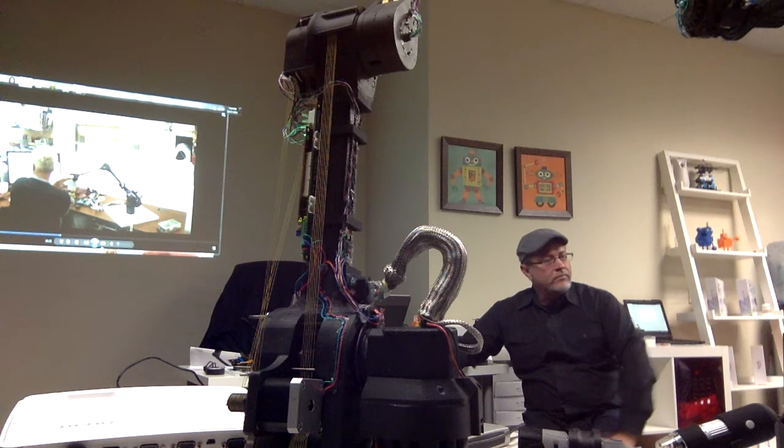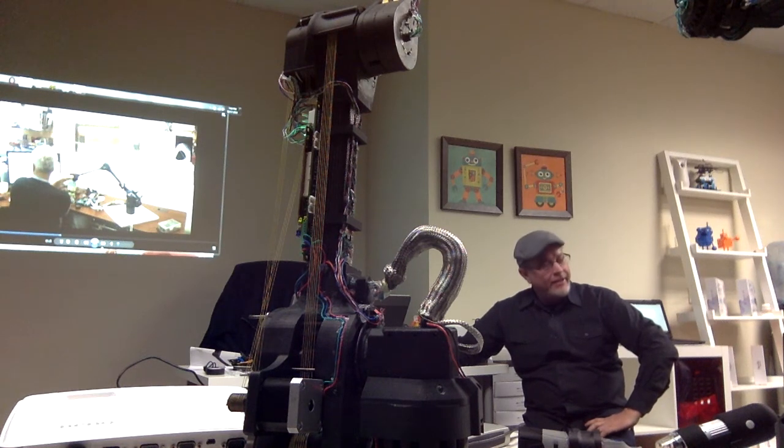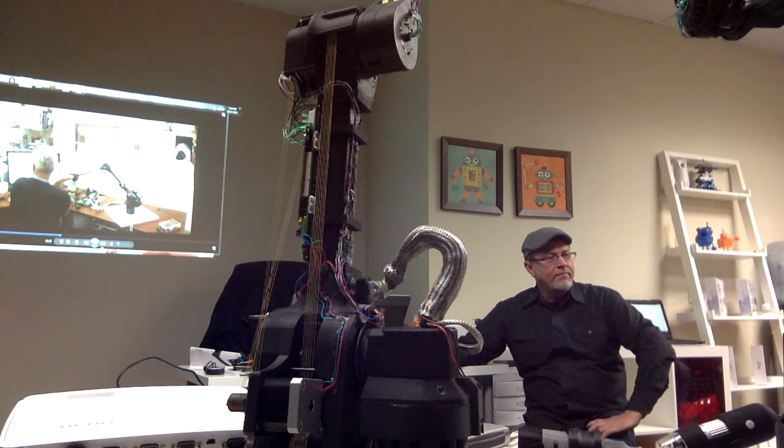So did you seriously 3D print parts for 120 different robots, or did you have them cast? We are printing right now as we speak. We've got a little 3D print forge factory. So we're burning out the 3D printers almost every 6 weeks. We like their warranty. So one of the things I've run into myself in playing around with 3D printers is it takes forever to print, and then I want to make a bunch of that. So I started off by trying to 3D print a mold, and then casting plastic into that. Unfortunately, the plastics that I wanted to use bonded to the mold, so I ended up printing the positive part, making a silicone mold, and then casting plastic.